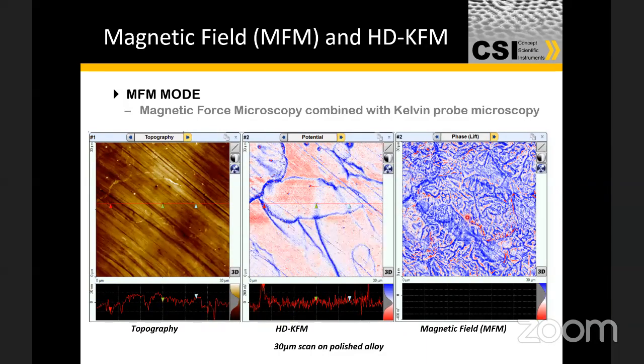What we're trying to highlight here is that we can now simultaneously make all three of these measurements. You can look at topography, the surface potential of the surface, and interrogate its magnetic response, really in the matter of doing the same scan in atomic force microscopy. Typically, some years back, you would be doing 3, 4, 5 different experiments to get some of these data. But now we're able to leverage the electronics we have today in the digital world to make a lot of these measurements simultaneously.